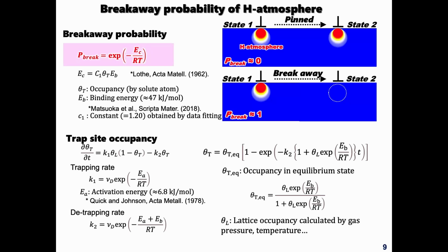The breakaway probability that a dislocation can overcome the atmosphere is given by this Arrhenius type equation. And by reference to the Lothe's work, EC includes the binding energy multiplying the trap site occupancy. This trap site occupancy can be calculated by the McNabb-Foster equations. And I confirmed that the hydrogen trapping, detrapping state can be regarded as almost equilibrium in the loading frequency ranging from 0.01 to 1 Hertz. So I can use the trap site occupancy in equilibrium states given by this equation.